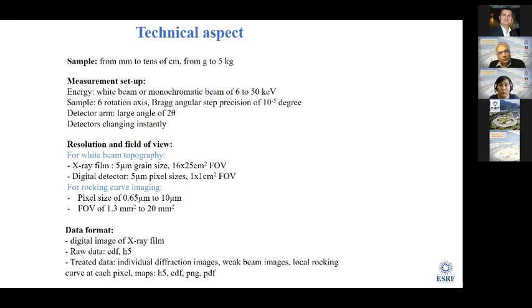We can tune our monochromator from 6 to 50 keV. For the sample, we have very good resolution. We have 6 rotation axes, and especially the Bragg angular step precision can go down to 10^-5 degrees. This gives a very good resolution for the rocking curve imaging, and the detector arm can go to very large Bragg angles. Then we can choose either different energy or different reflection, and we have different detectors. We can change from one to the other within less than 1 minute.